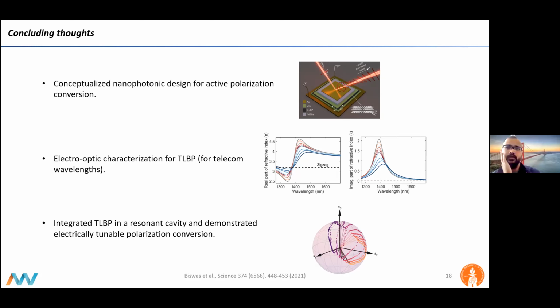Oh yeah. So first of all, I think this kind of opens a new direction for people to look at birefringent systems. So far people have been looking at anisotropic systems with respect to polaritons, where they look at hyperbolic polaritons and they see the propagation. One of the challenges of using things like hBN and molybdenum trioxide is that those are basically phonon driven birefringent systems. So it's very hard to electrically tune those transitions or those susceptibilities.